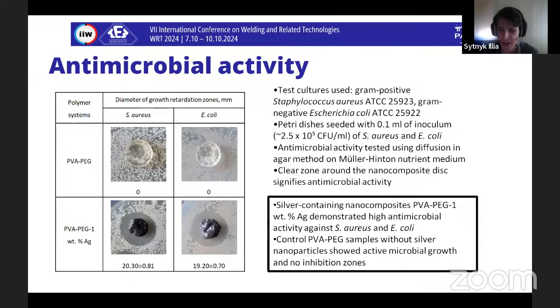As a result of studies of the antimicrobial activity of silver-containing nanocomposites, it was established that the studied samples demonstrate high antimicrobial activity against the studied test cultures of microorganisms. Thus, after 24 hours of incubation of the samples at 37 degrees Celsius, a clear zone was observed around the discs of the investigated silver-containing nanocomposites, which indicates the inhibition of growth of microorganisms. The diameter of growth retardation zones was roughly 20 millimeters for both Staphylococcus aureus and Escherichia coli. In control samples of PVA PEG, which did not contain silver nanoparticles, active growth of test microorganisms and the absence of zones of growth retardation were observed.